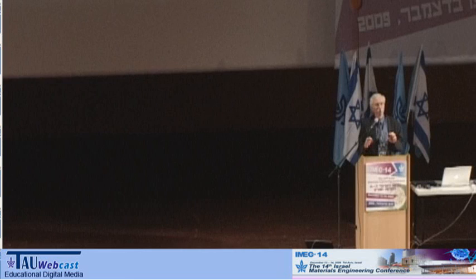Well, you know, if you have big pores mixed in, these macrophages seem to go into the spreading mode, and we get more scar. So again, it's quite optimized at the moment. It's a very tight range. We call it the sweet spot between 30 and 40 microns. And you know, when we use polydispersed materials, we just don't get this same reaction. It's a very tight little zone that gives this excellent healing response.